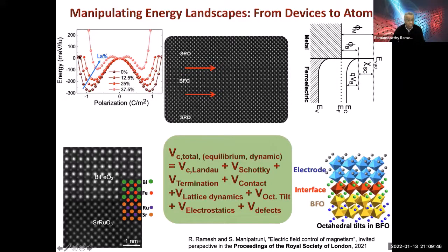We can tune the Landau potential with chemical substitutions. Lanthanum does a very good job of that, so that's not a problem. I think we can tune it to a large extent. But one of the things that we didn't realize until we wrote that paper is that the Schottky barrier, strontium ruthenate for example, forms a Schottky barrier. And therefore, you can have potential drops at the electrode-ferroelectric interface. So we introduced a layer of LSMO into that material to manipulate the Schottky barrier. That becomes important. That's something we need to worry about, the electronic structure.